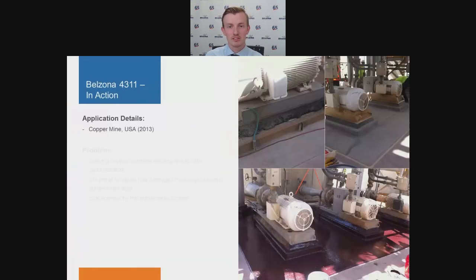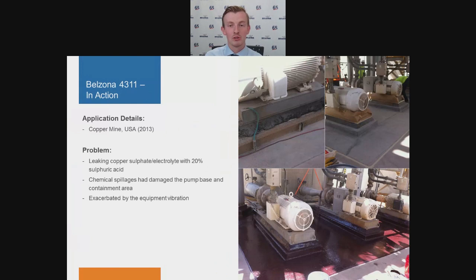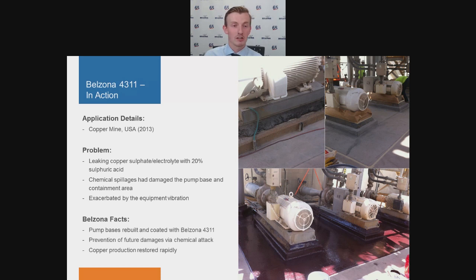Okay, so here's the third example. This one was a bund area for some pumps carrying sulfuric acid. So what had happened is the pumps had leaked and damaged some of the concrete on the plinth, on the base supporting the pumps. Due to the vibrations of the pumps, the damage was actually propagating and becoming worse. So before it got to the stage where they needed to do some serious reparation that would require structurally repairing the concrete, what they did is repaired it with the Belzona paste grades just to reinforce the plinths, and then they applied the Belzona 4311 coating to give the chemical protection to prevent any further damage.